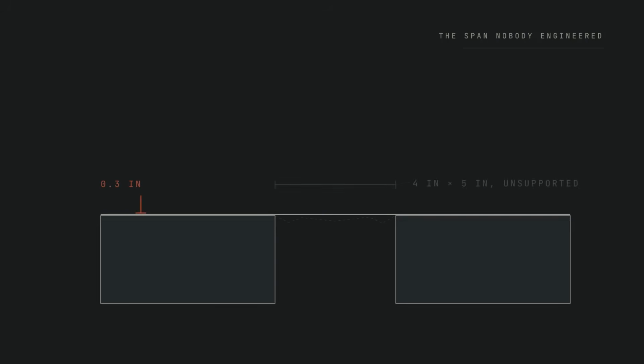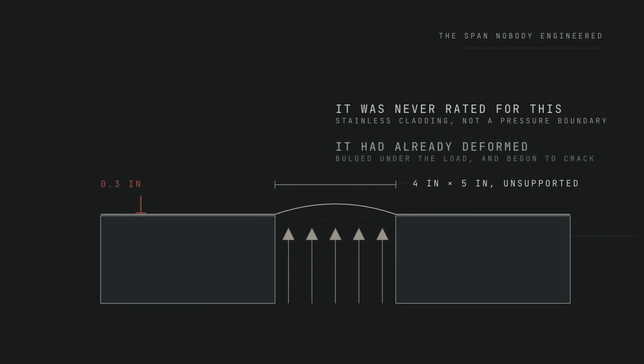Cladding is not designed to be a pressure boundary. It is a corrosion barrier, a coating with a job description. Nobody engineered it to take 2,000 pounds per square inch across a 4 by 5 inch unsupported span. It was doing a job it was never rated for. It had already started to deform under the load, and it had begun to crack.